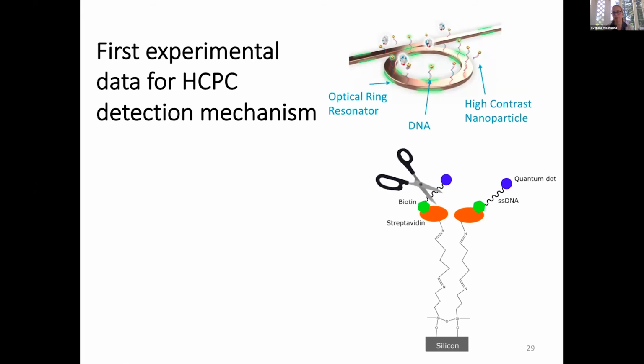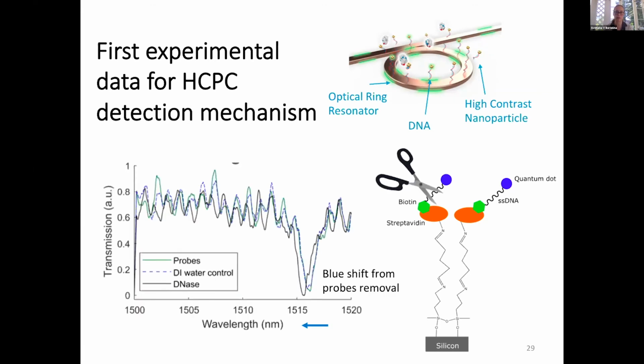Then we introduced DNase, not CRISPR in this case, but a similar enzyme that cuts through the DNA chains. And we could indeed detect the shift of the resonance in the ring because of cutting of the DNA. If we were just trying to wash it off with water, because this bond existed and the bond was not cut, there was no change in the spectrum. So we can see that we can reliably detect this signal that is caused by cleavage instead of addition of material. And this shift is actually huge. So this can be very easily distinguished from the noise, and it creates no problem in detection.